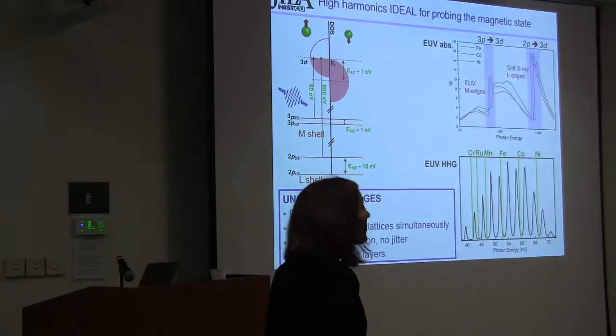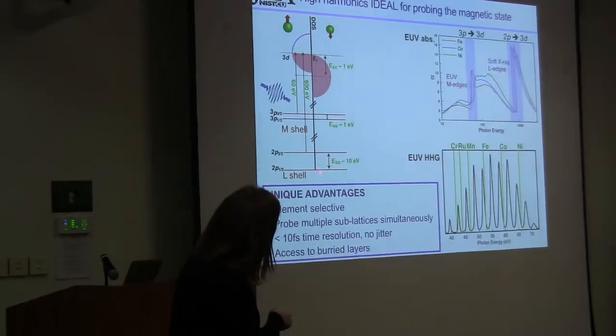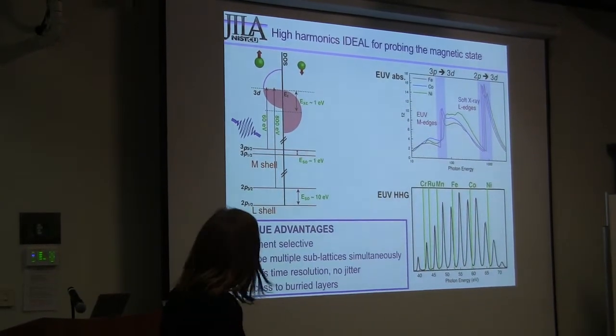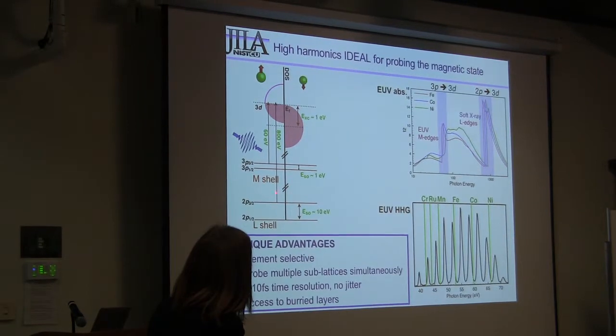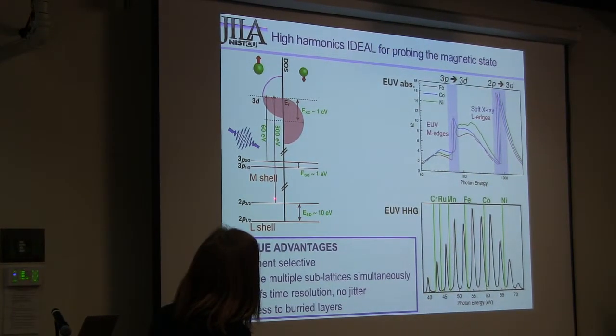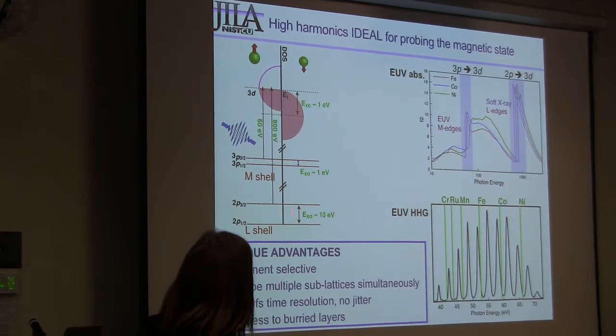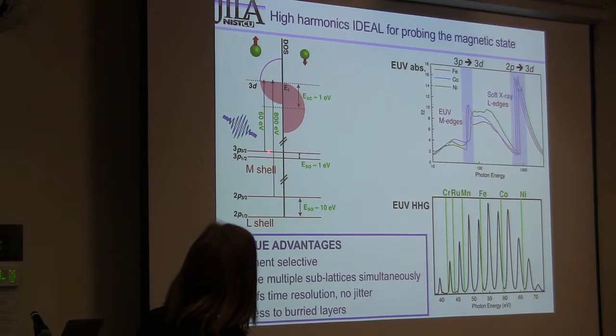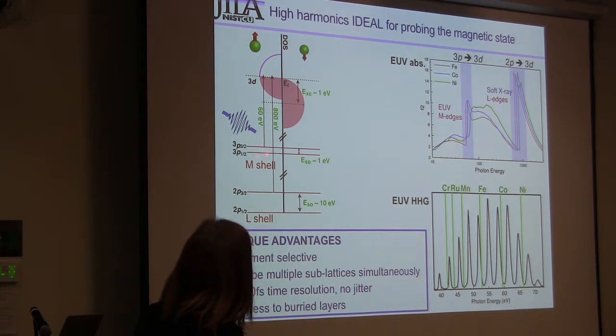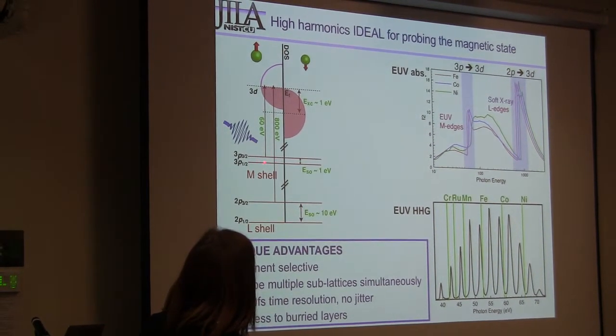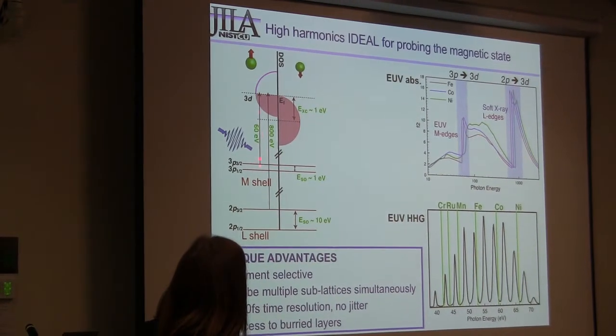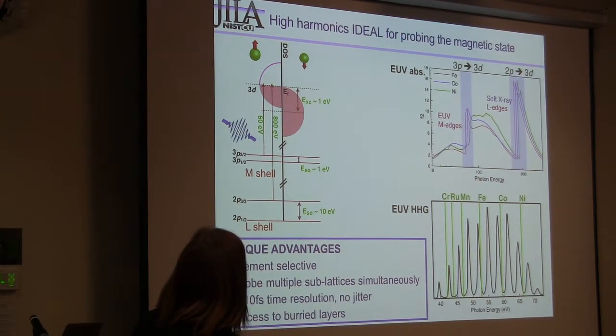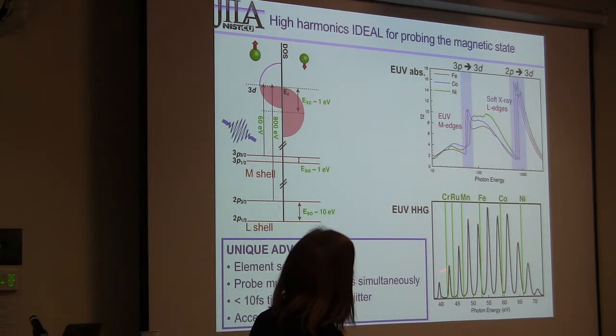So how do we measure the magnetic state? We can't use the L shell. We can make harmonics there, but at too low a repetition rate to make good measurements. So instead we use the M shell. This is the L shell here, and this is the M shell, 3P for example in iron. When we irradiate, we're measuring either the transmission or the reflection corresponding to these transitions. And if you look here at our harmonic spectrum in the extreme ultraviolet region, you can see that very nicely we can overlap with nickel, cobalt, iron, manganese, ruthenium, and chromium, all at the same time.